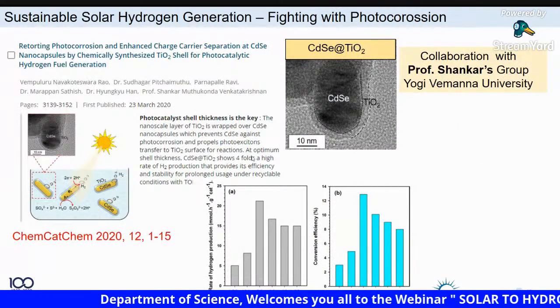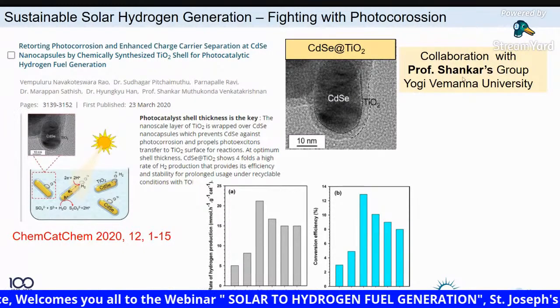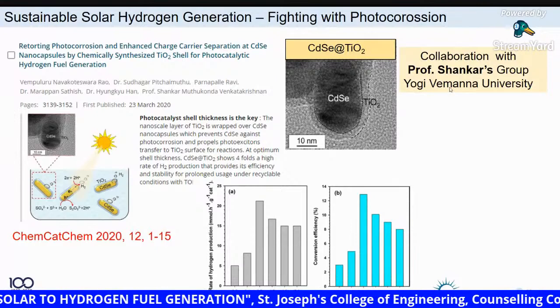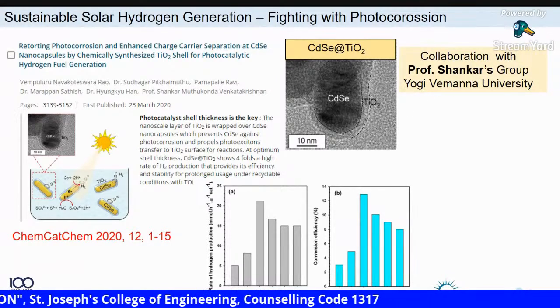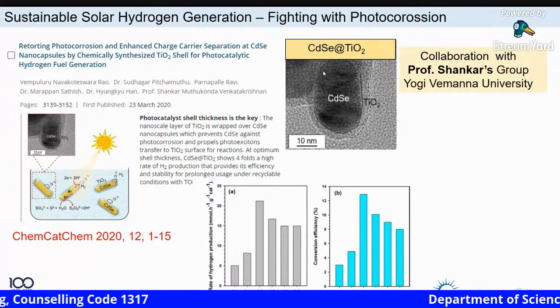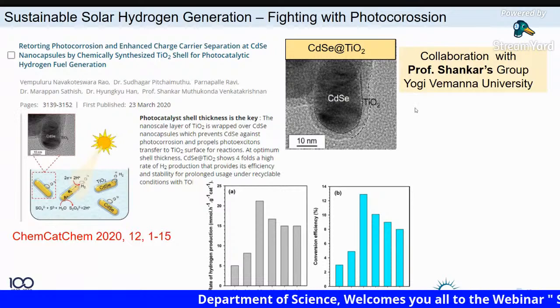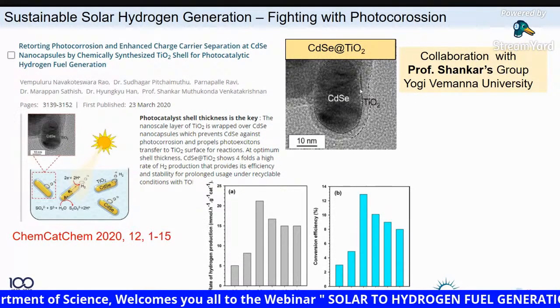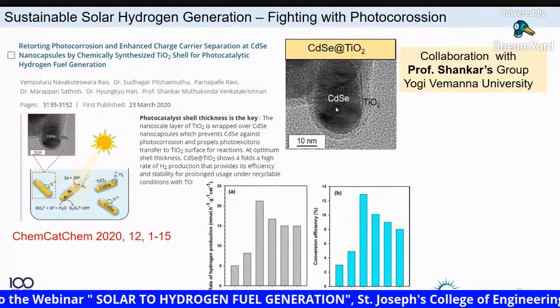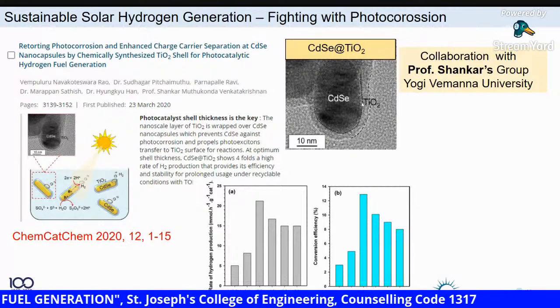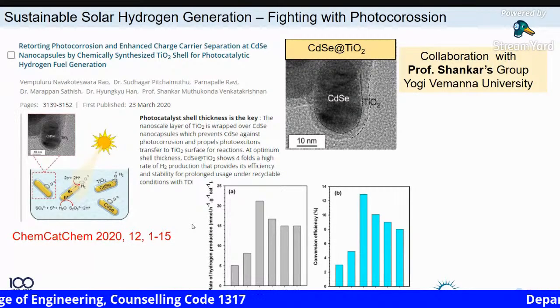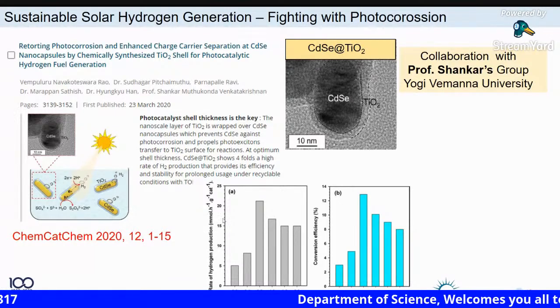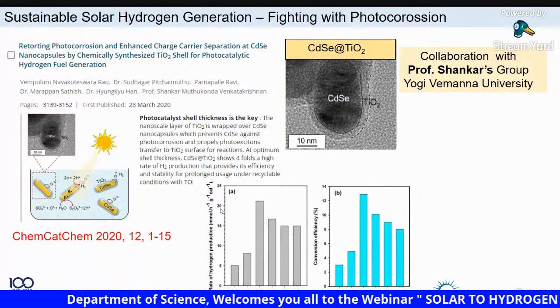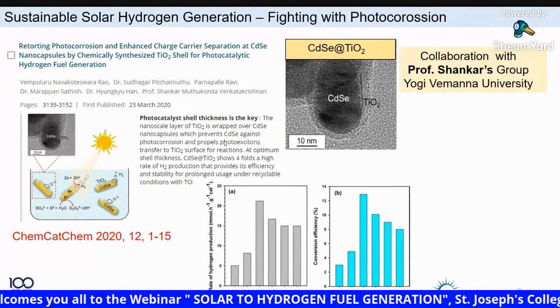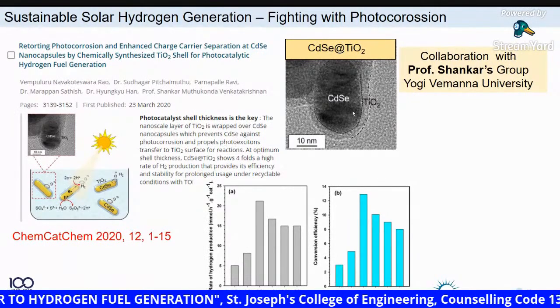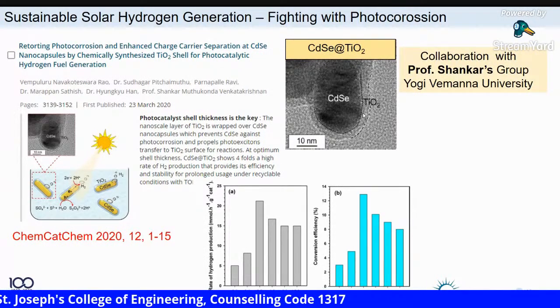So very recently this year, a few months ago, my group and Professor Shankar's group from Yogi Vemana University, Andhra, they are an amazing group in material chemistry. They developed a capsule-shaped photocatalyst material, that means cadmium selenide. So they developed the titanium dioxide passivation layer. It's highly protected. So we tested this system, how this titanium dioxide protects the photocatalyst material in hydrogen fuel generation. So you can see it's a really good amount of hydrogen fuel developed at different thicknesses of titanium dioxide. Okay, this is another example of how the protecting layer will help long radiation against photocorrosion.